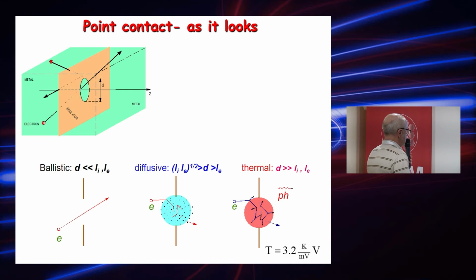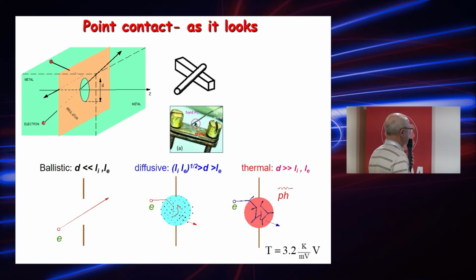So we investigate, we use two kinds of point contact in this investigation. The simplest procedure of creating point contact is to create mechanical point contact by touching two pieces of samples. Here is a photograph of the experimental setup. Here is the small point, the sample, and here is the wire which touches these samples. In this way, it's possible to create point contact.